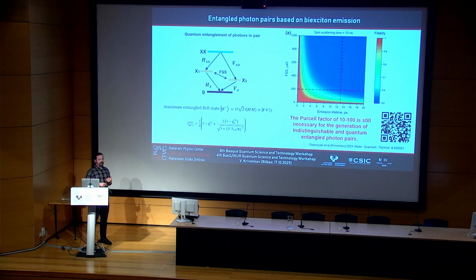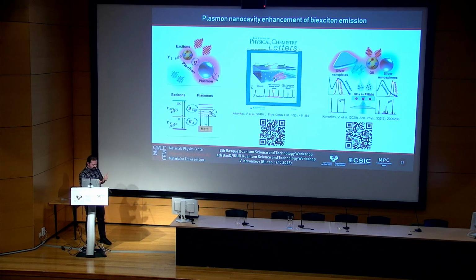So we still need 10 times more to achieve some levels of the entanglement fidelity, but it's still work which we are performing. What can I say about the coupling of these biexciton transitions to the plasmonic particles? First interesting thing is that plasmonic particles have broad spectra, broadband, so we can couple both biexciton and exciton transition to the same cavity mode, which allows us to increase the efficiency of both emitted photons.